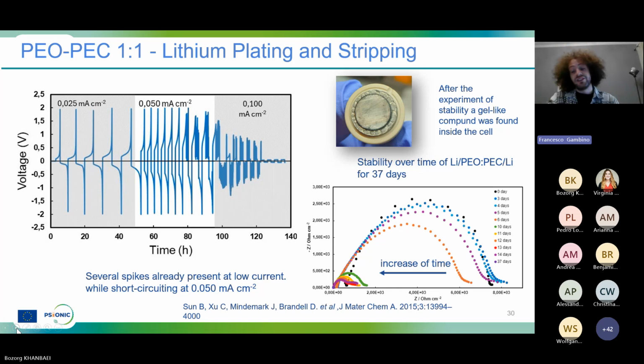To investigate this, we also assembled an identical cell and we recorded the impedance over a period of 1 month. And we can see from the graph on the bottom right that the internal resistance of the cell is continuously increasing. This can be explained by the low stability of polycarbonates in contact with lithium. They are known to be degrading and depolymerizing, producing the starting monomer. Next slide, please.